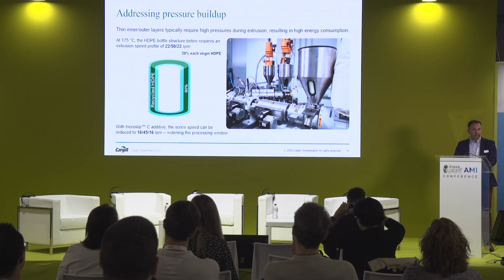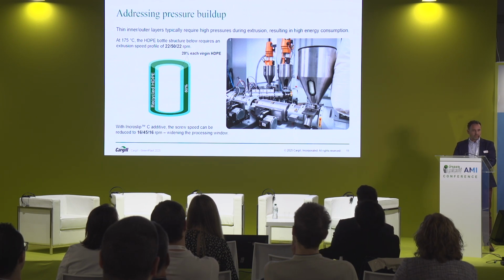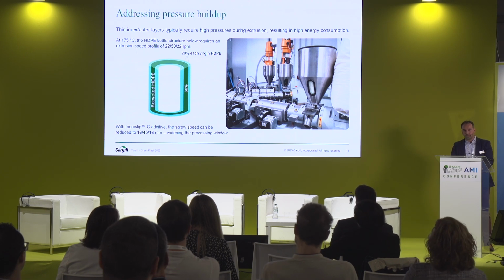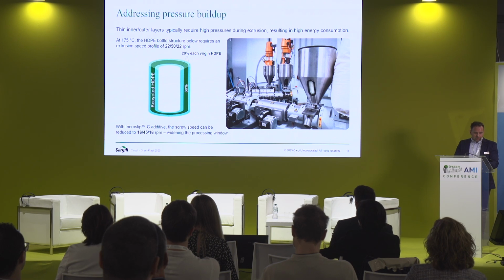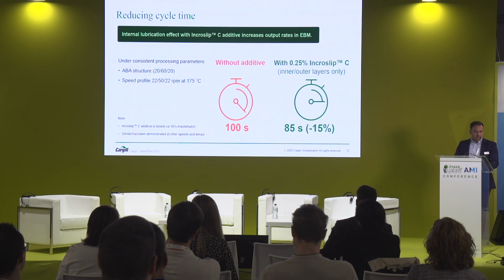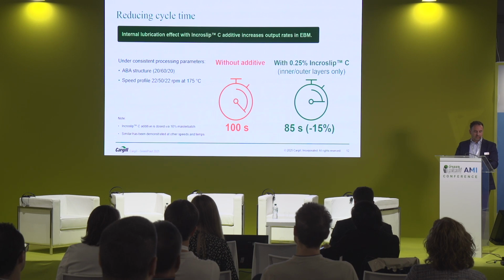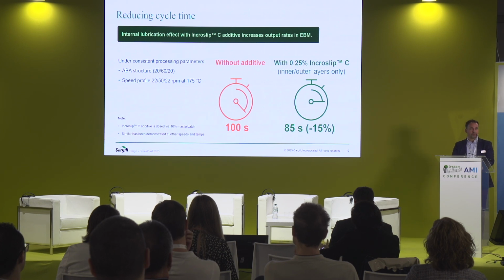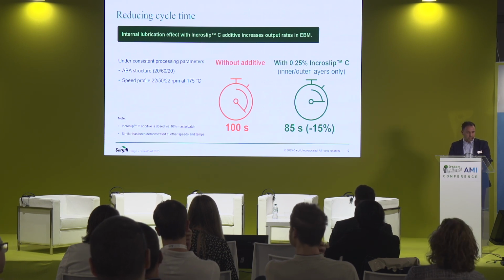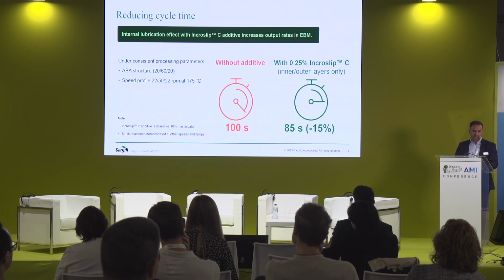Straight away, we reduced the temperature significantly because this should be the aim for all converters, to save energy and to protect the polymer from degradation. We found out straight away that with the use of the additive, we would use different speed profiles, we could widen the processing range, and that is a positive thing. More importantly, we could see a reduction of the cycle time. So for the same conditions, without the additive, we needed 100 seconds to make the bottle. With the additive, that was reduced to 85 seconds, a nice and clear 15% reduction. This is quite common in general with the right use of our additives, that you can improve the output rate. And this is something nicely demonstrated in the EBM bottles.